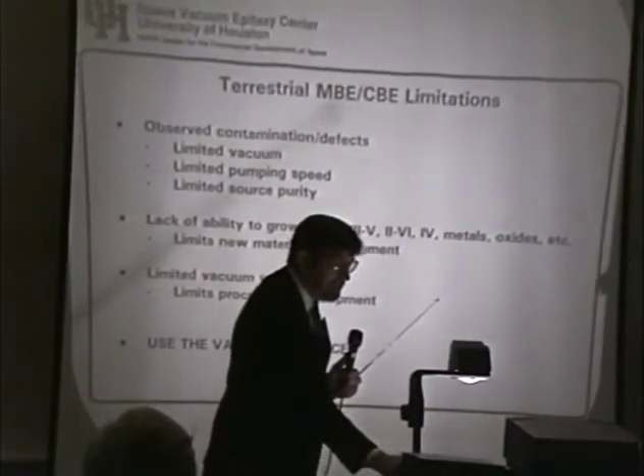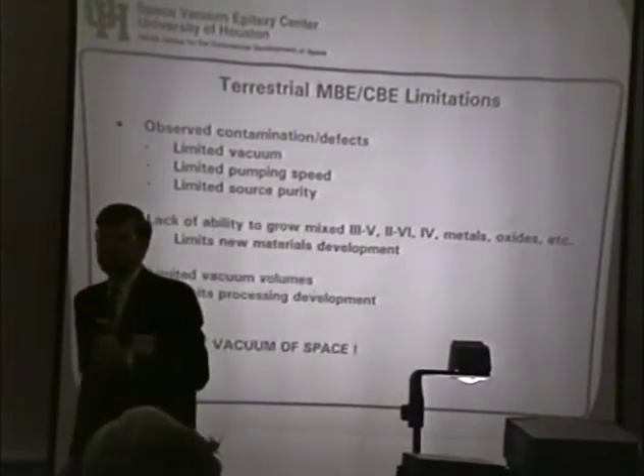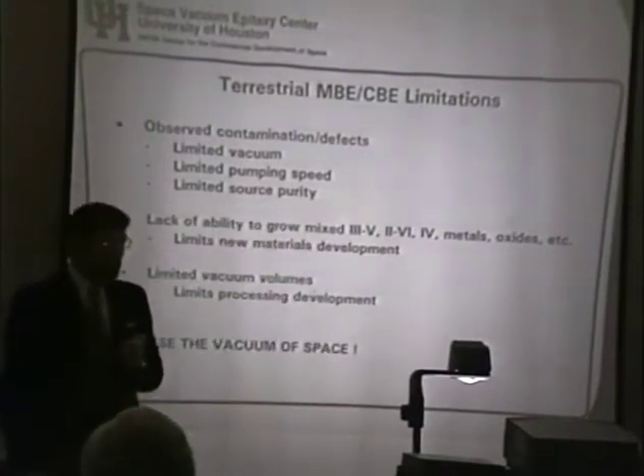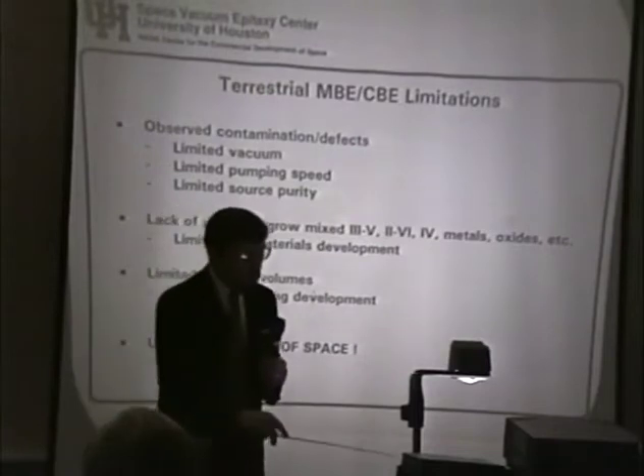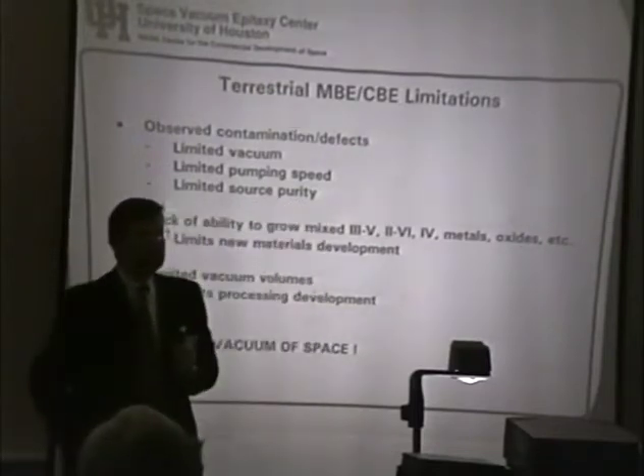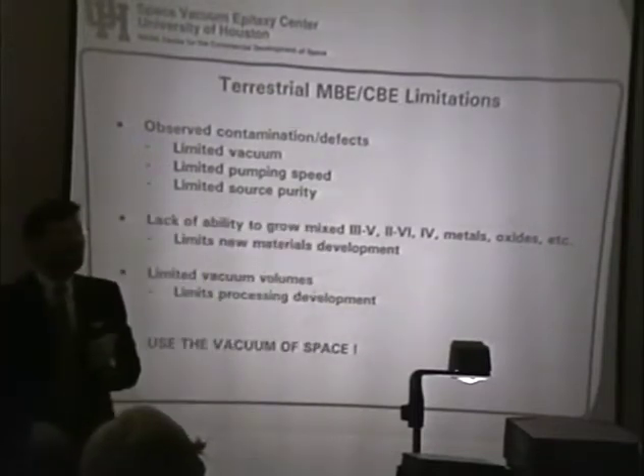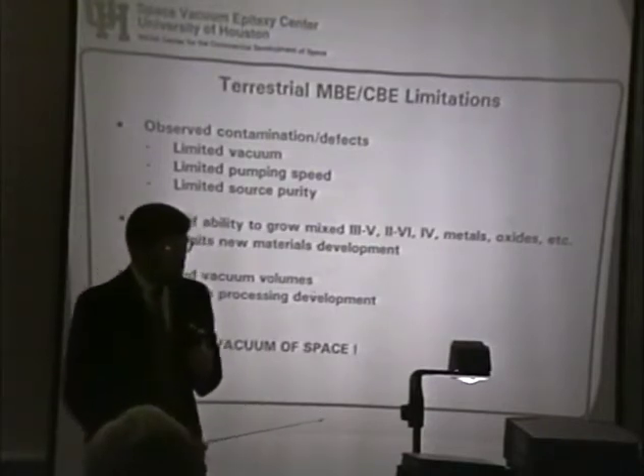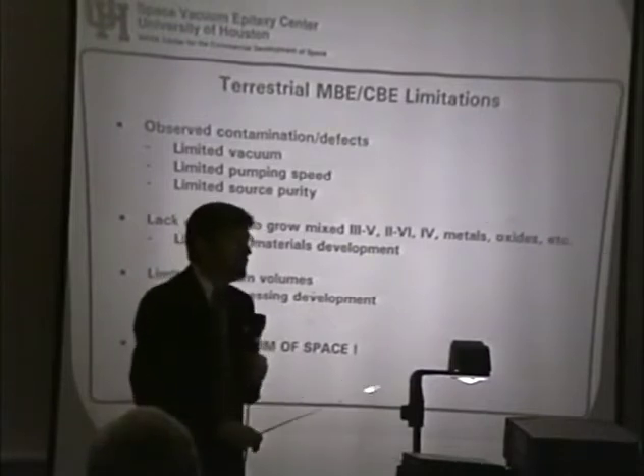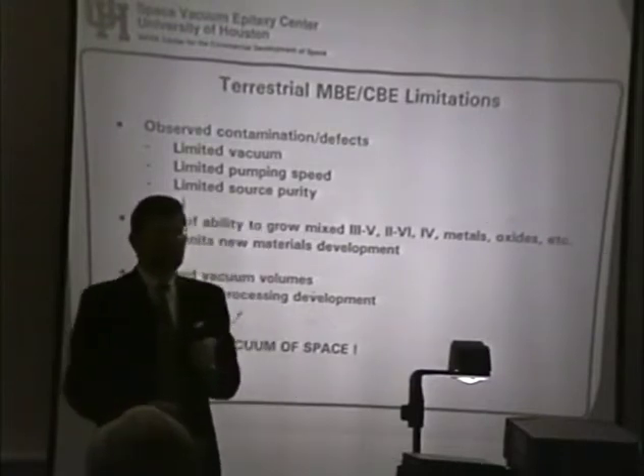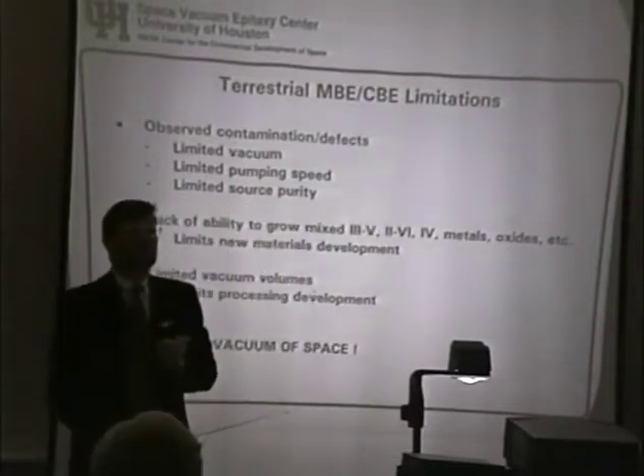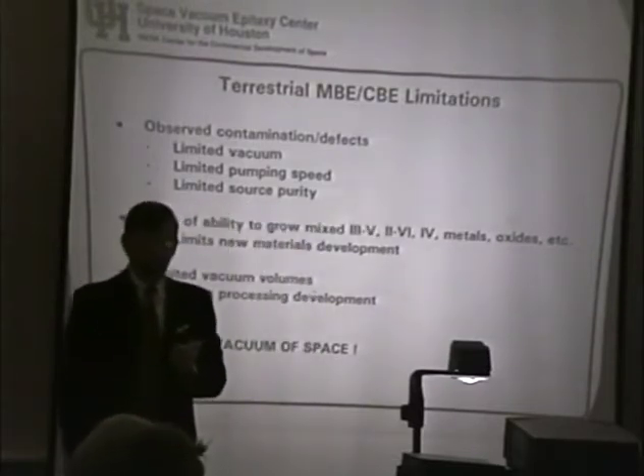Well, since the technique has been around since the late 70s, why haven't we seen many more of these advanced materials applied in our current technologies? I classify that as some terrestrial limitations to this epitaxial growth technology. The materials that are made, the best ones that are made, are still not good enough. And that's because we have limited vacuum terrestrially. We have limited pumping speed, the ability to remove contaminants from that vacuum environment. And we have limited source purity. The starting materials have to be pure to begin with, so you don't contaminate the environment by the source materials.